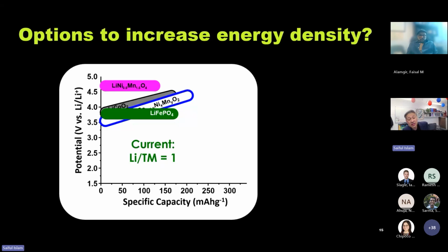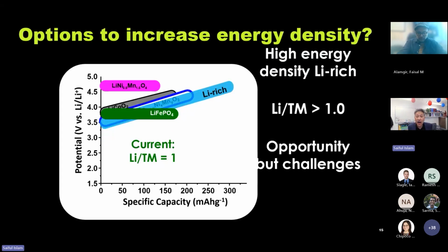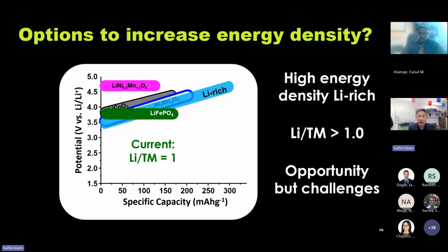But all these materials have a lithium to transition metal ratio of 1. The lithium-rich materials have a higher ratio of greater than 1, but also a higher energy density. As you can see, in principle, the theoretical capacity can reach as high as 300 milliampere hours per gram, so higher energy density. So this is a real scientific and commercial opportunity, but, and there's a big but, they present challenges.